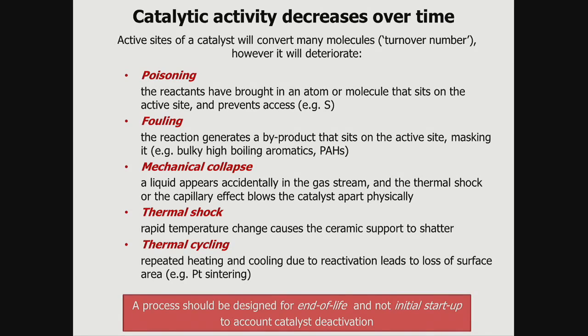One of the most common errors is that catalysts, which are at room temperature, are stuck in by a man with a JCB, or a lady with a JCB, into your reactor. They then turn them on and they heat them up, and they heat them up above the boiling point of water very quickly. So you now steam the catalyst. So you've now got very active water molecules inside the catalyst just bashing the structure apart.